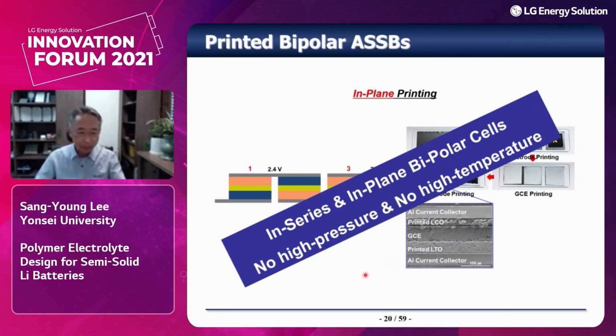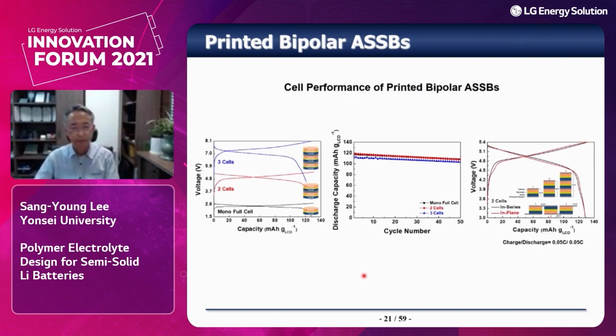And throughout the whole process, we did not rely on high pressure and high temperature processing conditions. So here are the electrochemical properties of our cells. As you can expect, the one cell, two cells, and three cells show an increase in the operating voltage, and then the cyclability was stably preserved. In addition, no significant difference between in-series and in-plane cells was observed.